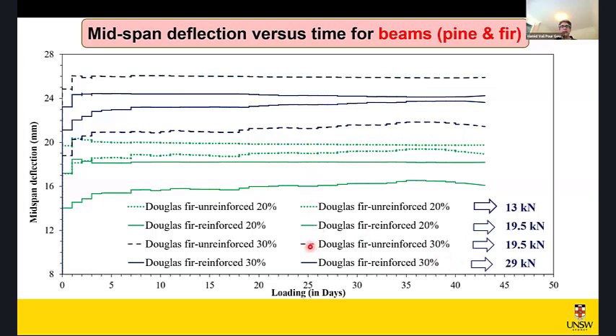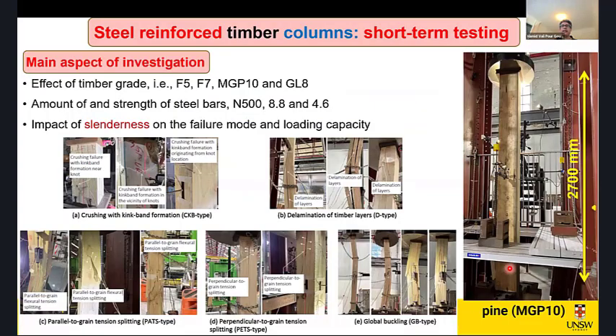But let's compare this again, dashed line with the solid line. You see the peak displacement or the maximum displacement after like 6-7 weeks is around 23 millimeter if you took the average, and it's more or less the same for the unreinforced and reinforced one, with the big difference being that in the reinforced case, we have 50% higher load applied. So it means that really steel is doing its job and taking the load and the stresses in the process. Then we did the short-term test on the column.